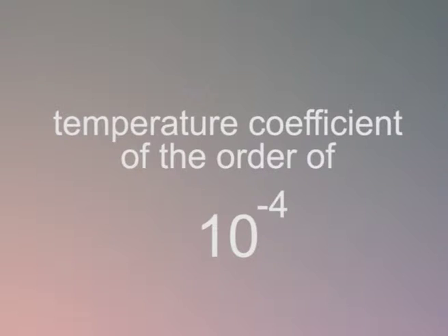A small sample is then deposited on a slide, immersed in a micro drop of oil and covered with a cover slip. In this method also, the selected immersion oil or liquid should have a temperature coefficient of the order of 10⁻⁴. Also, the oil must be stable across the temperature range under consideration. The slide is then put in the hot stage.